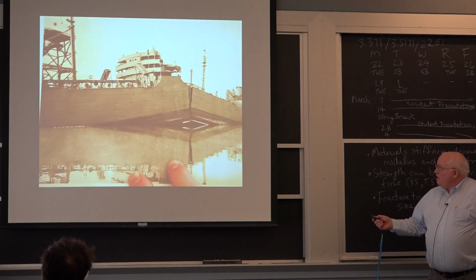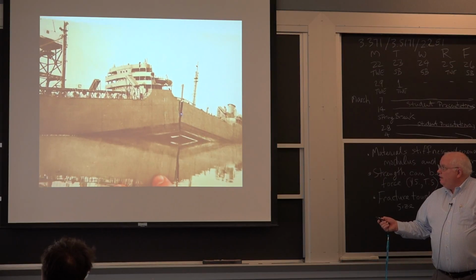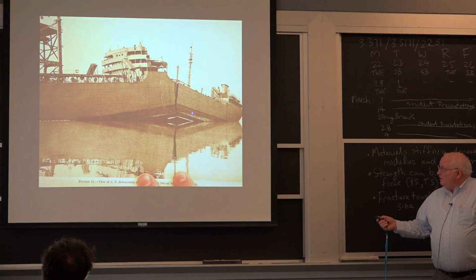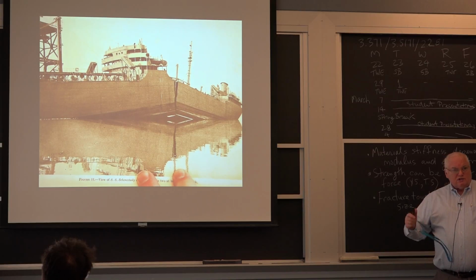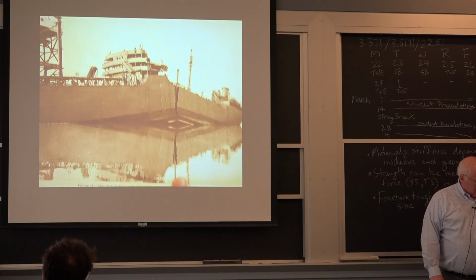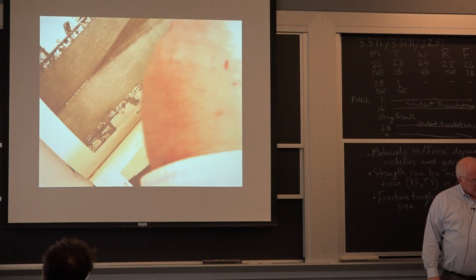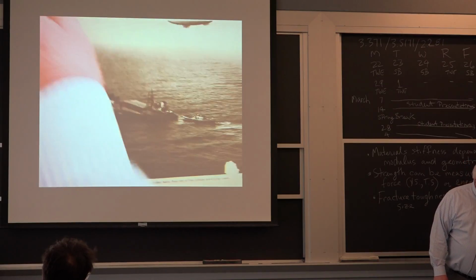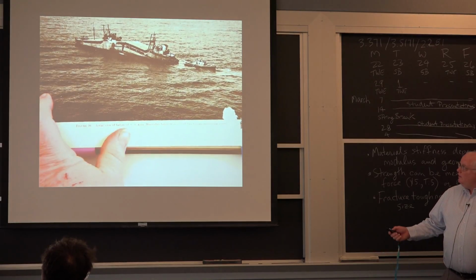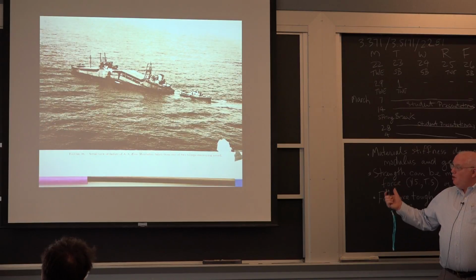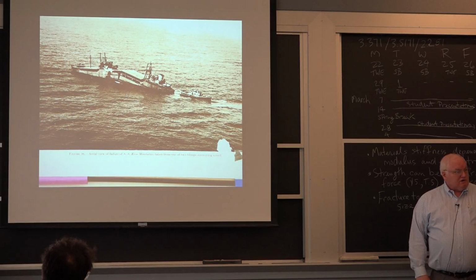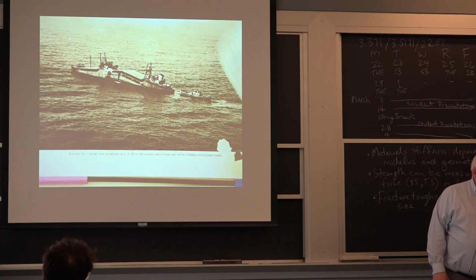It just decided to break in one day, as it's sitting at dry dock. And if you go to a fracture book, this is the classic book they usually show. What they don't show is one of the plates from this book of the USS Esso Manhattan, where the same thing happened out in the middle of the ocean, which was a lot worse than doing this at dry dock. So they lost a few ships, and they came in, they did a study.